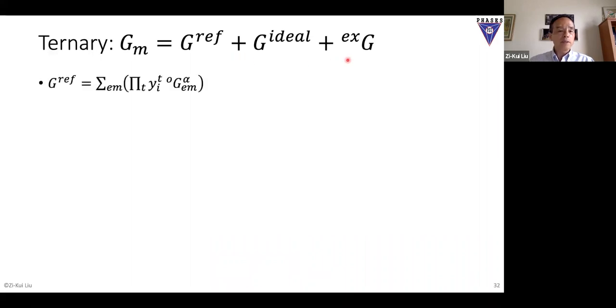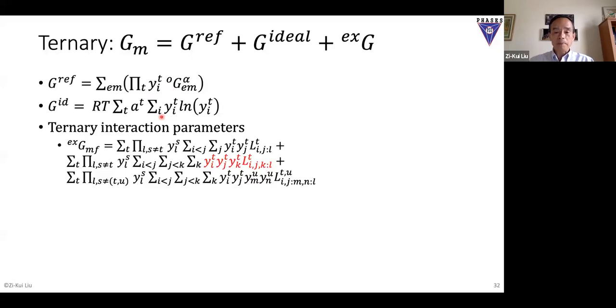We have the ideal entropy. Now, reference becomes more complex because you have so many different sublattices. The equation becomes a little bit complex. You have to talk about all the sublattice configurations, then the mixing in all sublattices, then the interaction in all sublattices. This is the ternary interaction term, you have the binaries, ternaries, and then you could have complex ternary interactions or even quaternary interactions too.